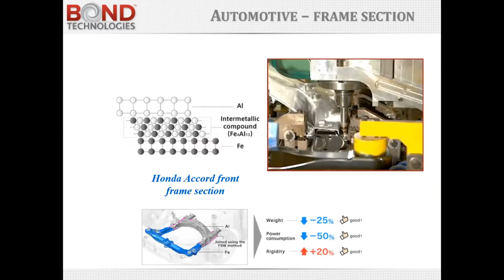Honda did some friction stir welding of the front K-member on the Honda Accord to join aluminum to steel. One of the things that happens when you join aluminum to steel is that intermetallic compounds can be formed. You may be scratching your head thinking, wait a minute, you said that the melt point isn't reached when you do friction stir welding, and yet the melt point of aluminum and the melt point of iron are drastically different. So what happens here is that the aluminum gets pretty hot, and the steel is really receiving a much smaller fraction of the heat input